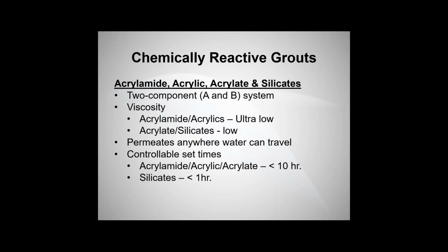Moving into the chemically reactive grouts now, those are comprised again of the acrylamide, acrylics, and silicates. They're always a two-component system, a part A and a part B. Viscosities are relatively close to each other. The acrylamides and the acrylics are ultra low, typically 1 to 2 centipoise. The acrylates tend to be 3 to 4, whereas the silicates can be upwards of 8 to 10. That doesn't sound like a large variance, but believe it or not, that can make a difference in your permeability into a soil. They basically permeate anywhere water can travel. There are controllable set times.